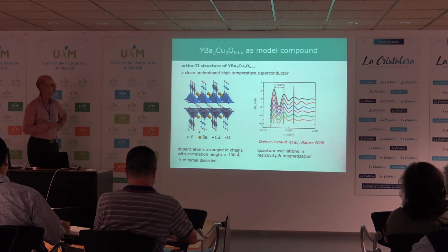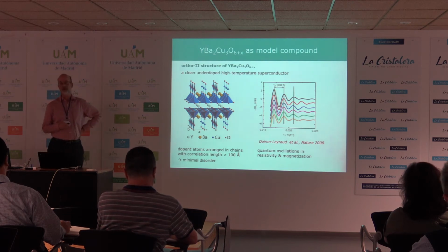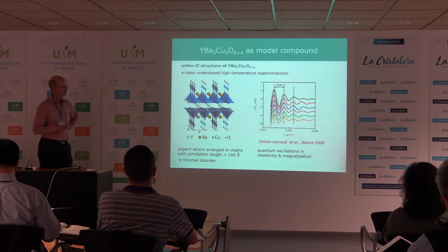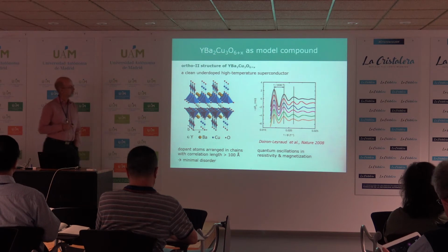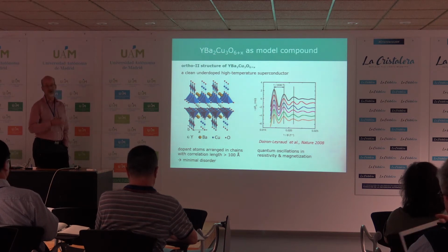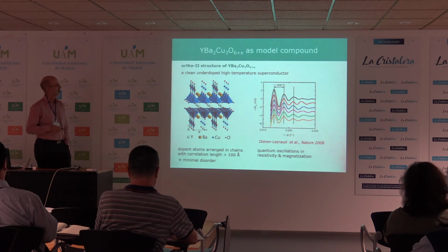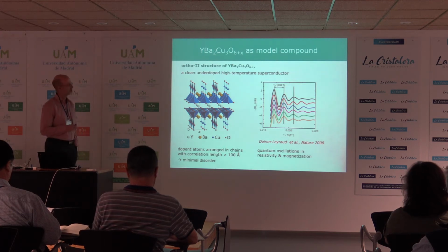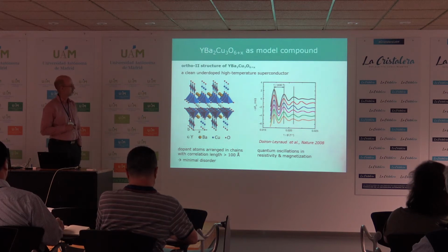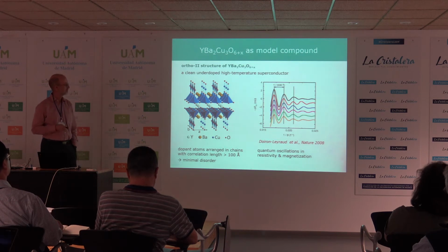Okay, so the manifestation of this minimal disorder in the YBCO system is the quantum oscillations that Cyril has already discussed, that you see even in underdoped. So in overdoped materials, several families exhibit these quantum oscillations, which are very sensitive, of course, to impurities. But this paper here, published by Taillefer's group, was the first to actually demonstrate quantum oscillations in underdoped systems. Now, there are a couple of other cuprate families where this is also being observed.